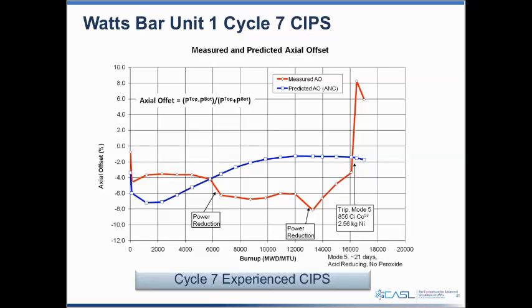So from 6,000 to 16,000, they were depositing boron. You're seeing the more negative axial offset. At 16,000 megawatt days per ton, they removed some crud, no longer precipitated boron, and you got that large increase.